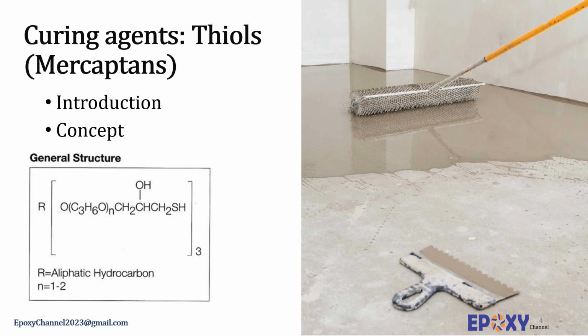Thiols improve film quality, production efficiency, and design flexibility of photo-curing resins. Mercaptans cure epoxies through active hydrogen on a sulfur group, SH, and typical mercaptan curing agents that are sold commercially have multiple SH groups available for curing. A representative structure of a commercial polymercaptan curing agent has been shown here.